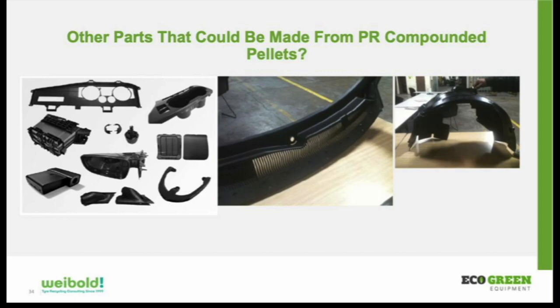So when we start looking at all the plastic parts just within a car, for instance, on the right here, to put it in perspective, one wheel well liner on a car is typically about 4 pounds. And there's four wheels, so you have four wheel wells, 16 pounds of material. If that's made with 50% rubber, now you have 8 pounds of rubber going into each car. And of this particular car here, they make 300,000 of these cars a year. So that's 300,000 times eight. That's a lot of pounds of rubber. And there is, by the way, a material now spec'd through Ford. It's a Ford approved material that does have crumb rubber in it. And they're utilizing that material at Ford with more and more parts being produced every day from that material.